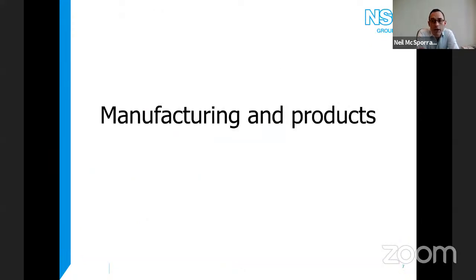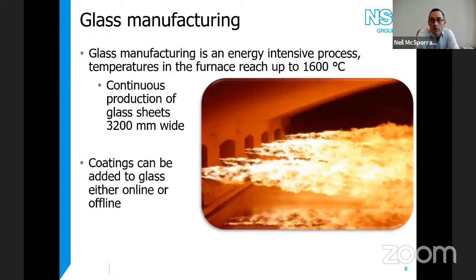So just starting off by thinking about manufacturing. I don't know if you're all familiar with the glass manufacturing process, but it's a very energy intensive process. The temperatures there reach up to about 1600 Celsius, and that's because we have to melt raw materials to provide the glass, basically. So we melt a mixture of sand and other components like dolomite and limestone and others to produce glass. And a lot of that melting is carried out by gas firing, as you can see in the photograph that I'm showing there. And that enables us to produce very large, optically clear pieces of glass in a sheet width of about 3,200 millimeters. So that's also continuous. So before we cut it, it's a continuous stream of glass coming out of the furnace.